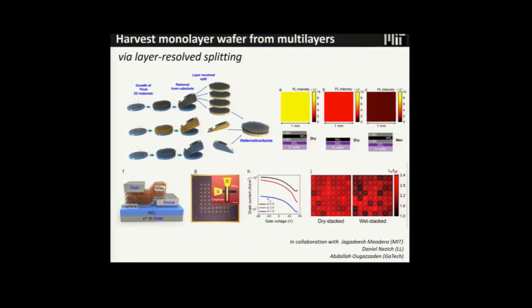Then we try to make some heterostructure by using this technique. So we encapsulate the tungsten sulfide with boron nitride at wafer scale, and compared to just monolayer tungsten sulfide transferred on oxide, it shows a much stronger PL intensity.